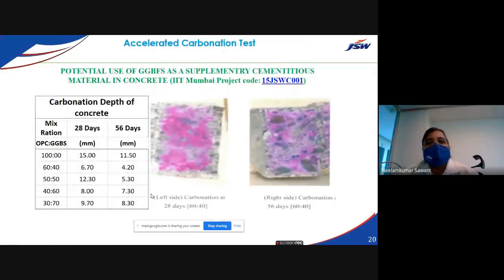Accelerated carbonation test. This is also important whenever concrete surface deterioration is concerned, because we want the durability as compared to the concrete strength. So carbonation depth is measured generally for the quality of concrete. If I am using the mix OPC and GGBS, with OPC 100% and no GGBS, after 28 days there is 15 mm carbonation, and after 56 days it is 11.5. These are the studies I have done.